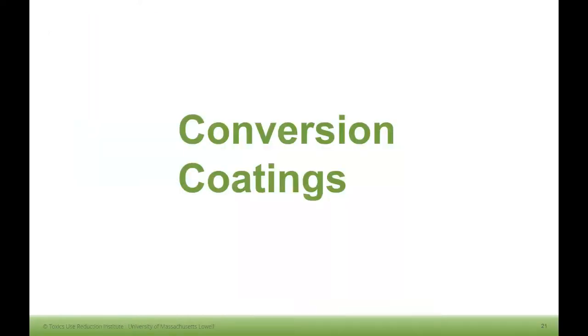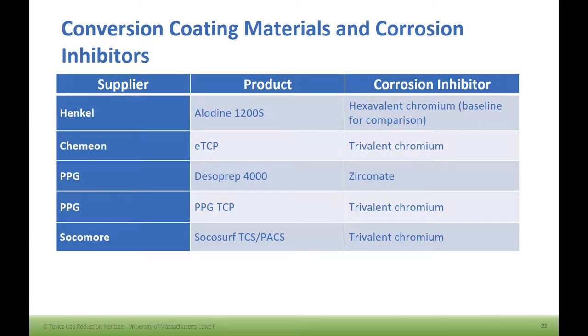The third application that we looked at is conversion coatings, and this is the one we're just finishing up now. We did some preliminary testing to narrow down the conversion coating materials, and we narrowed it down to five for more extensive testing. We used the Alodine 1200S as the baseline containing hexachrome, and four different alternative conversion coatings without hexachrome. Three are based on trivalent chromium technologies, and one is a zirconate.